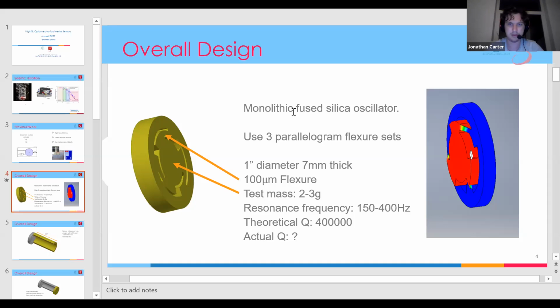So again, we can make these monolithically from fused silica. The design at the moment is about 1 inch in diameter, and either 7mm or 5mm thick, depending on our specific design, as I'll discuss later. The flexures themselves are about 100 micrometers thick, which is about the width of a human hair, and you can really see it on the devices when you look at them. And this allows us to suspend a test mass of 2 to 3 grams. The resonance frequency this puts it at is about 150 to 400 hertz.